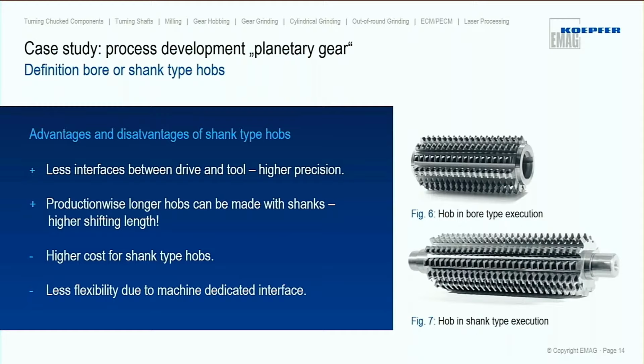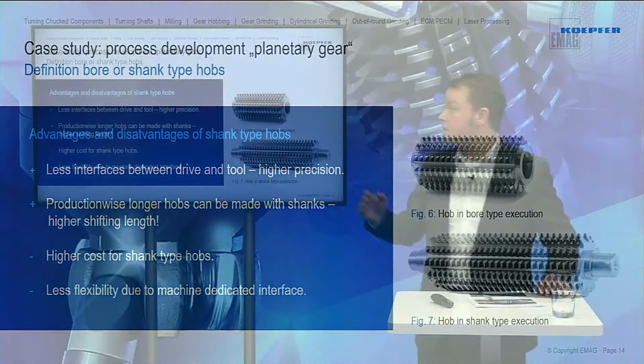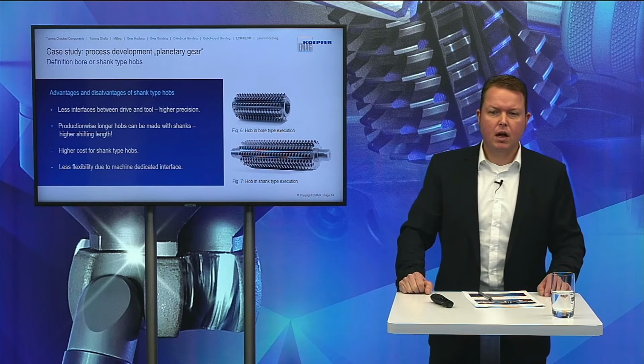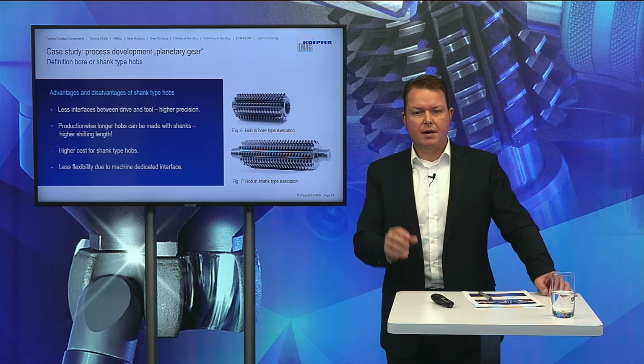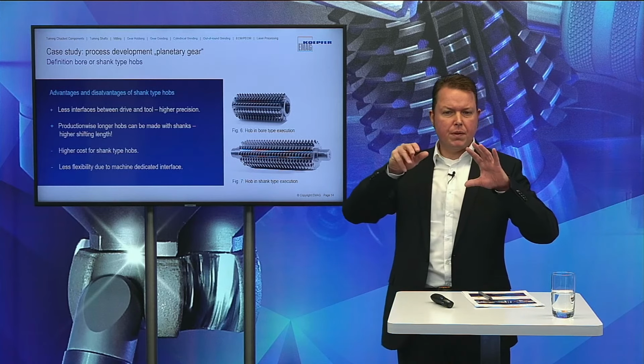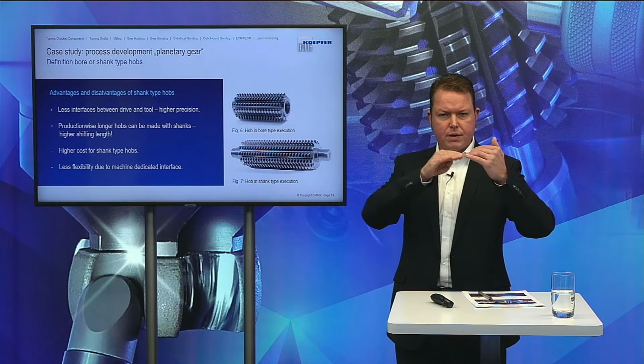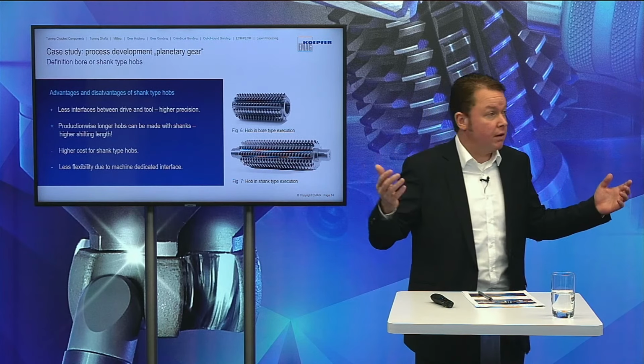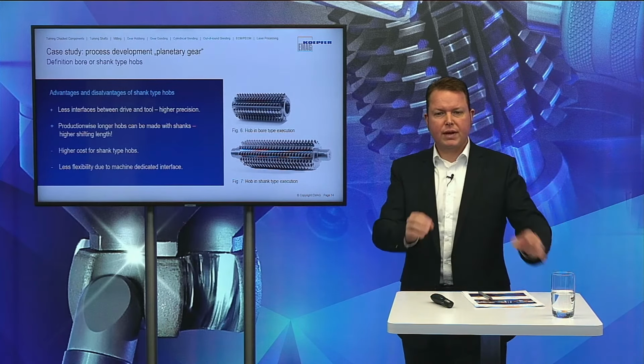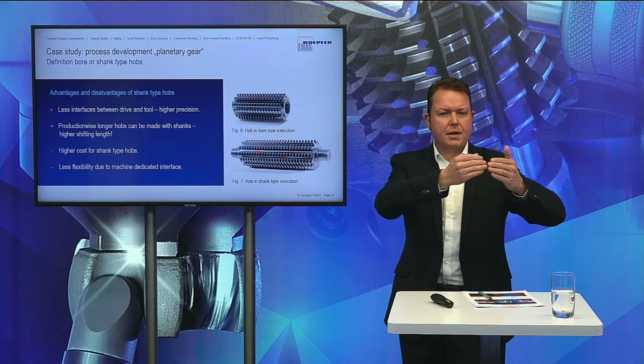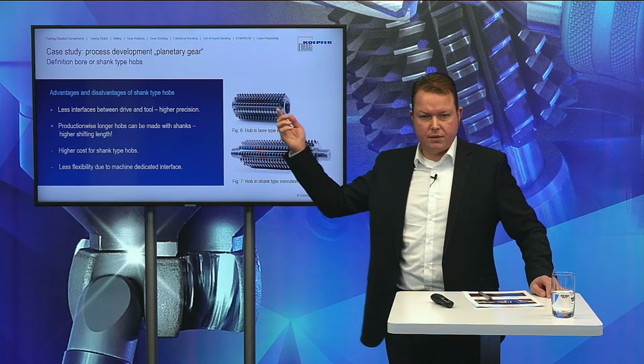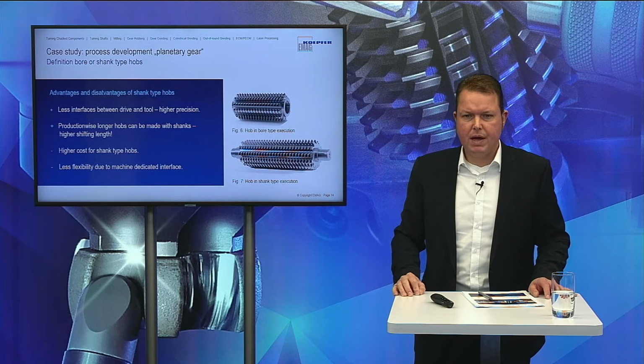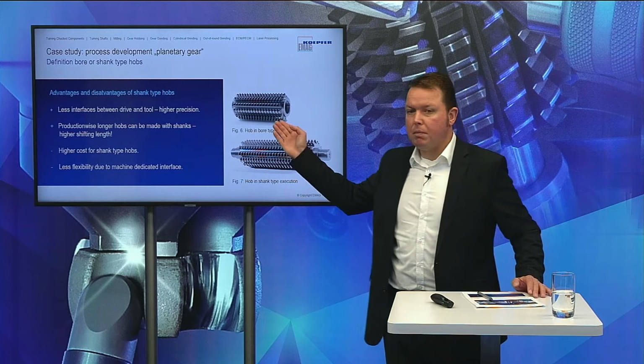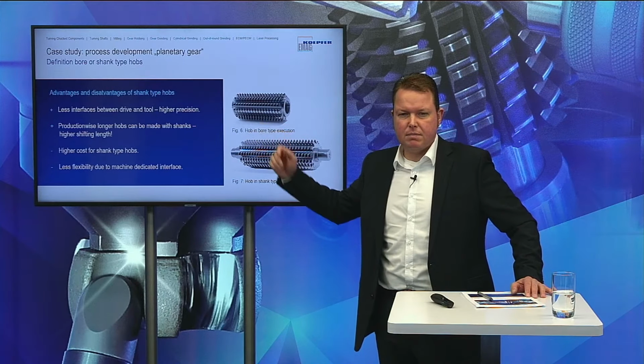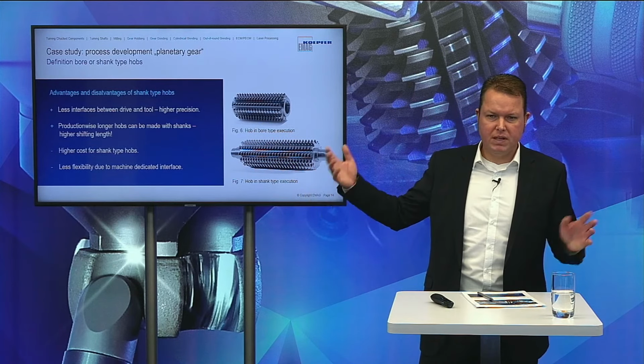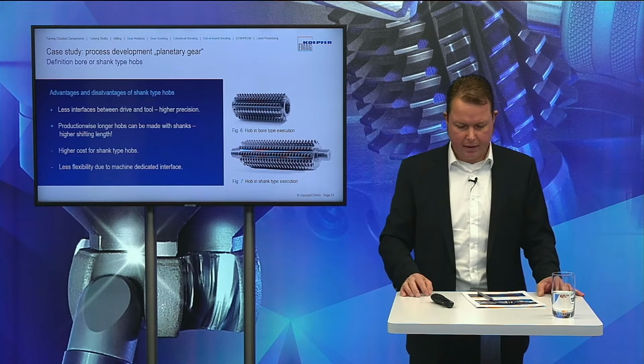It's the case because if we take a look at this bore type hob, here we see a picture of a hob with OD 40mm, bore size 16 millimeter. And if you have to hone this bore with a high degree of accuracy with reference to the external basic rack, that is already a very precise tool, you cannot do this until eternity, so length is limited. And we see this here, it's realistic pictures from hobs we have had on our machines already. The maximum length here is approximately 70, maybe 80 millimeters. Here we have some 200, if not 220 millimeters of length.